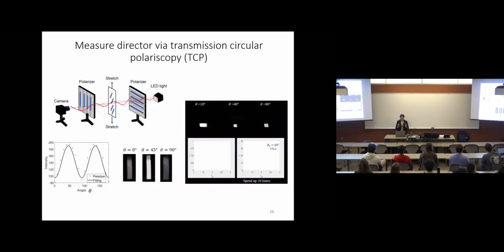Let me first show you the result of TCP. We use TCP to capture the director orientation, especially how it evolves while you are stretching the material. Mainly we have two crossed polarizers, and depending on the angle of the director, you can either see a dark field when the director is parallel or perpendicular to the polarizer, or you can see a bright field when it is at 45 degrees. What I'm showing you here is the TCP result. By measuring this line intensity, we not only obtain the stress-strain relation, but also capture how the director is evolving with respect to the external strain.